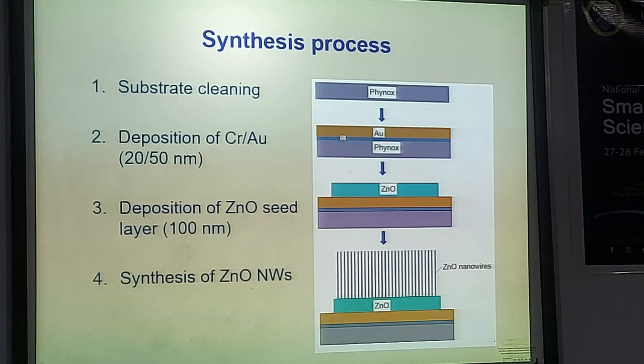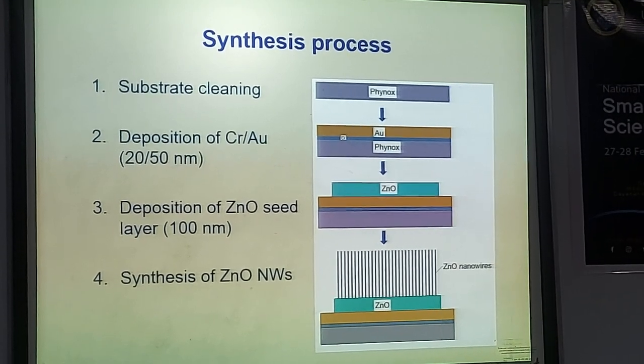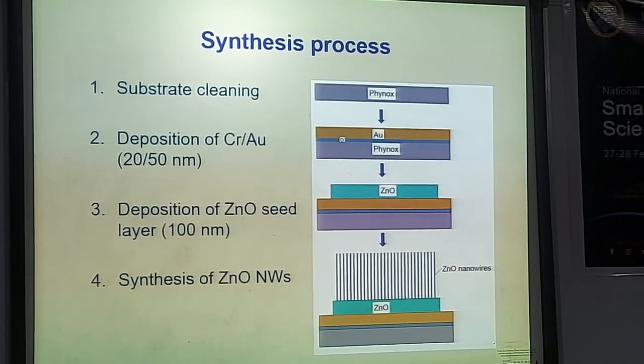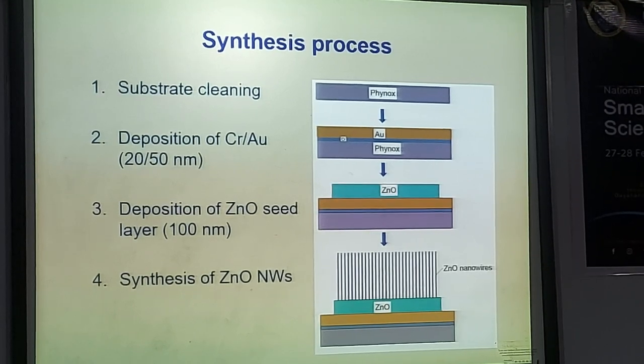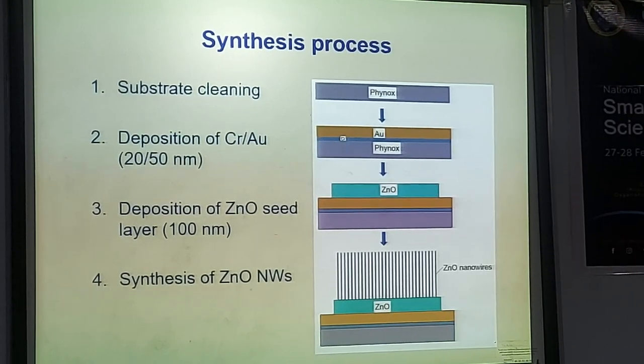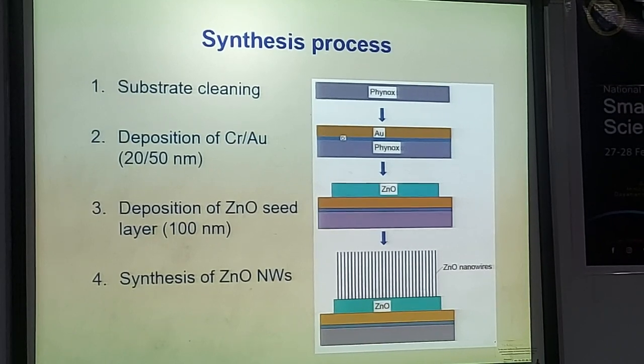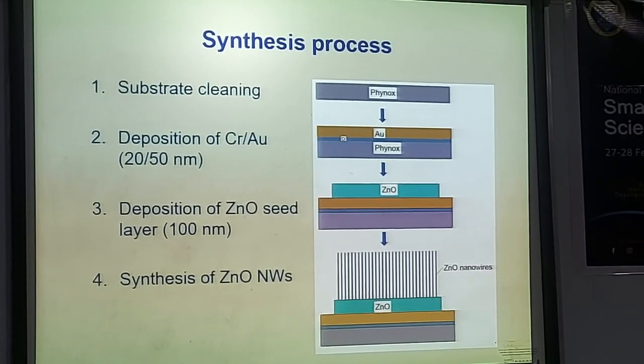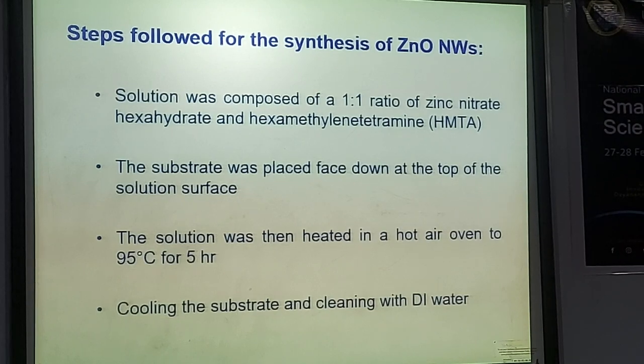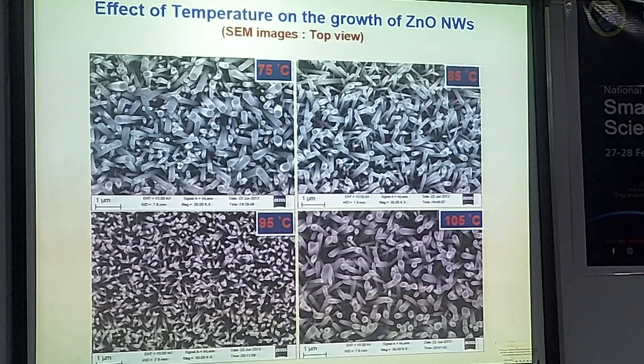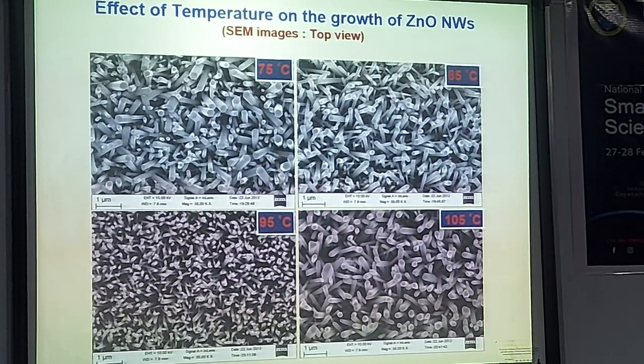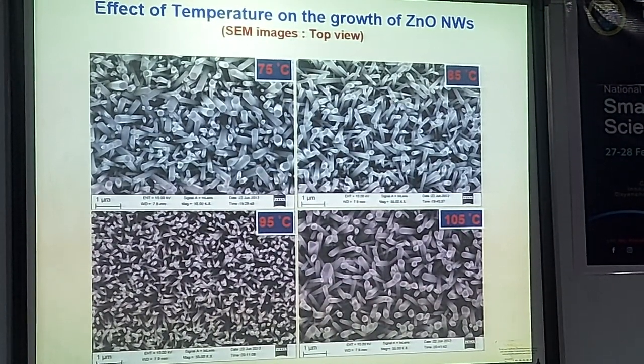Substrate preparation and cleaning, deposition of chrome gold with a chromium layer for adhesion, and then deposition of zinc oxide as a seed layer of 100 nanometers, and we synthesized by a controlled temperature process to grow zinc oxide nanorods. These are some of the process steps for the synthesis of zinc oxide nanorods. And these are the electron microscopy pictures, top and side view, of the zinc oxide nanorods that we could synthesize.